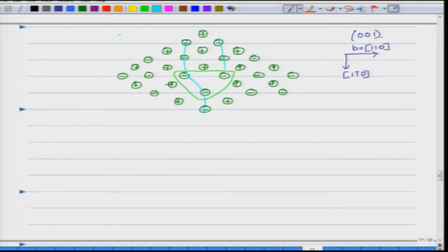So, what do you see over here? This is the structure. Because there are charges, you see there are 3 planes here and on the bottom there is only 1 plane. So, here 2 planes with opposite charges are missing at the bottom. One thing to realize is that an edge dislocation is now clearly different from a non-ionic system, in that you have 2 planes missing.